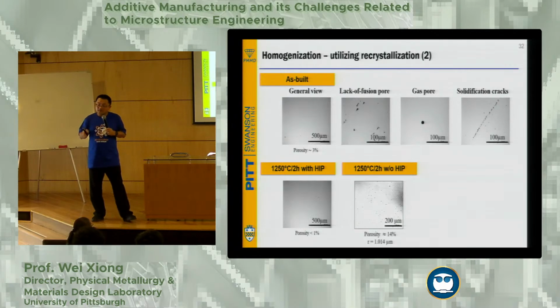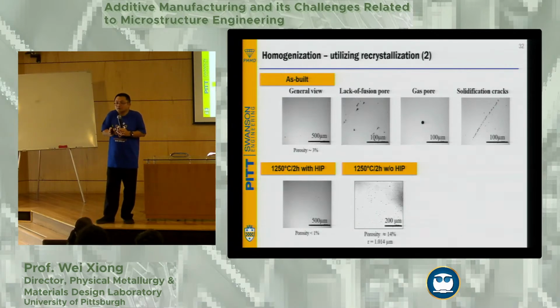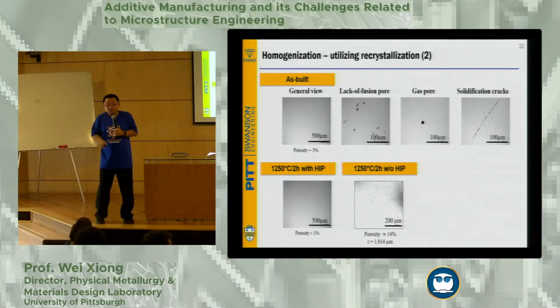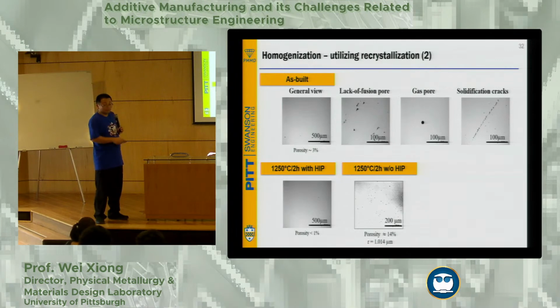A little bit of over melting - if you cannot have a perfect melt, I would like to introduce a little bit of over melt rather than lack of melting. The reason is because if you have these lack of fusion pores, no matter what you do, during the aging process, post-heat treatment, these pores will start to appear again.